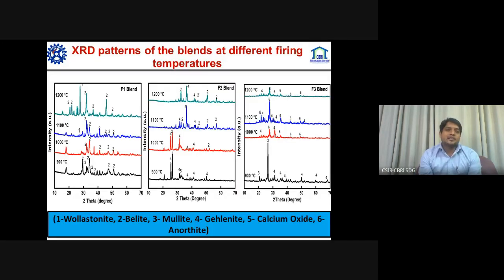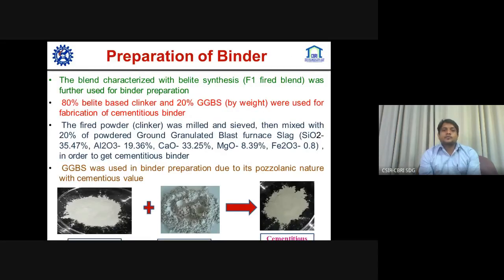So in the XRD analysis, for the F1 blend, it was observed that at 900 degrees C, the Belite was prominent, but at the very high temperature of 1200 degrees C, it was converted to bredigite in F1 blend case. So at 900 degrees C, we can get Belite, and in case of F2 blend and F3 blend, there was a synthesis of gehlenite and anorthite, and this is due to the presence of alumina in boiler ash and fly ash. So from the synthesized clinker, the binder was prepared.